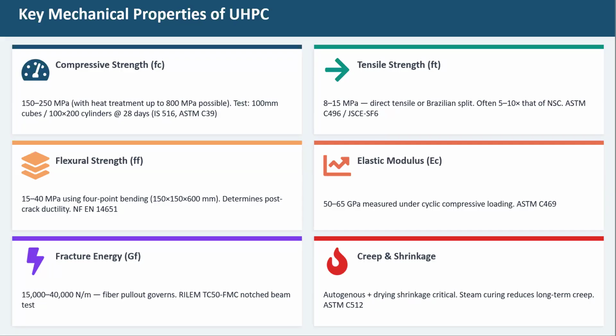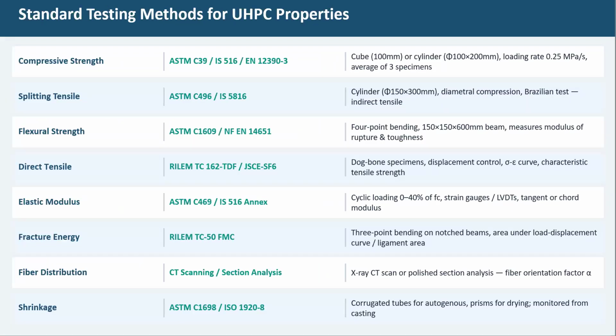And coming to the standards of testing, we have different standards across the globe. So mostly you can prefer either ASTM standards, which is a standard one, or you can also go with Indian standard codes as well, which will give almost an equal range of testing standards. But again, when we are testing with any standard protocols, let's say if you are following ASTM standards, make sure you are testing with the average loading rate that is specified in the code conditions. Because if you are testing at a loading rate that is just whatever you have availability with, that may not yield better strength or better properties also.